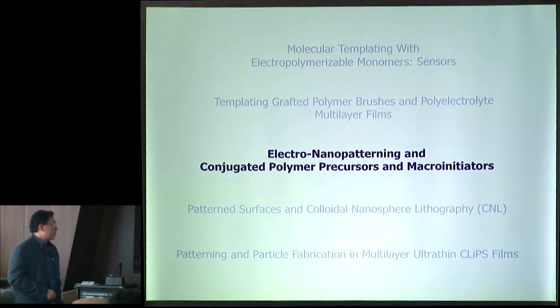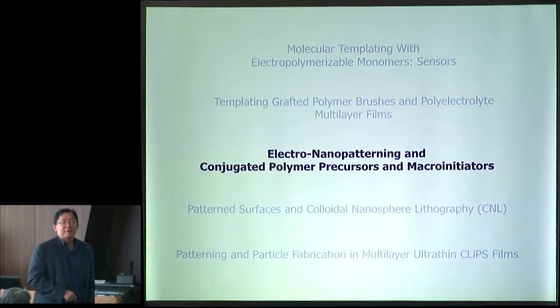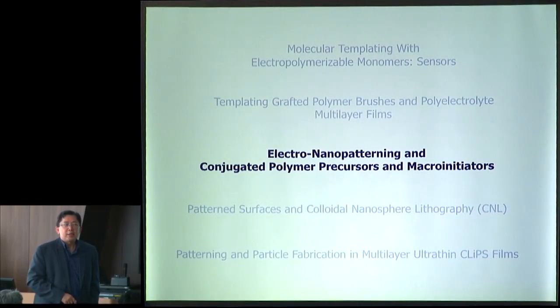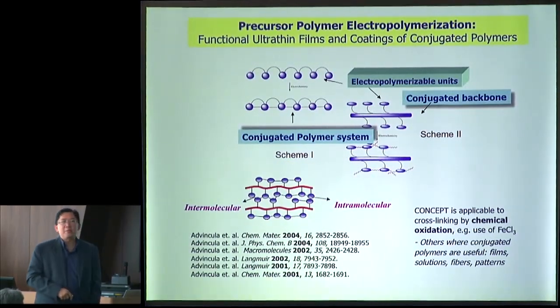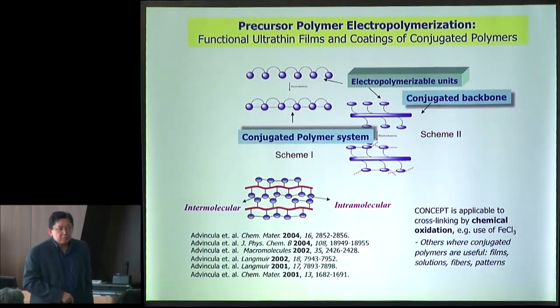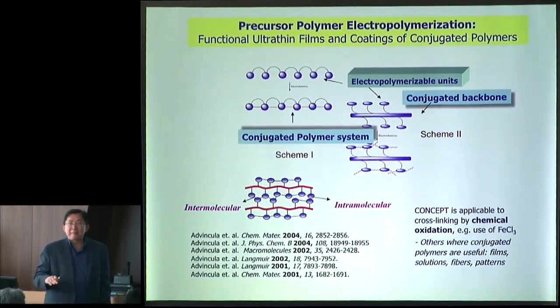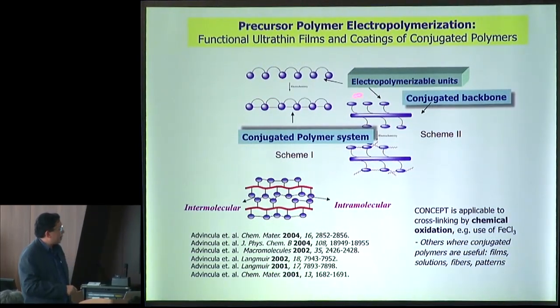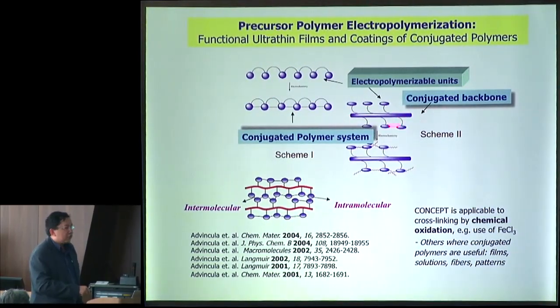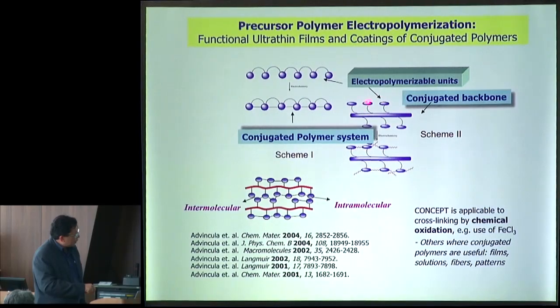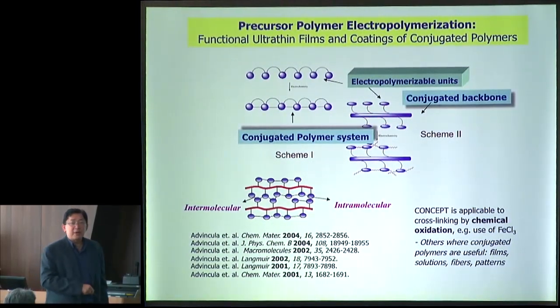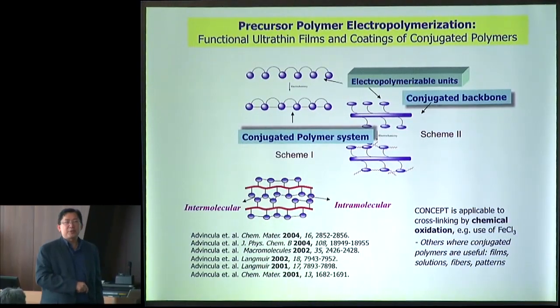Electronanopatterning and conjugated polymer precursors and macroinitiators. One of the things we developed very early in my group is the use of electropolymerized monomers attached to a polymeric backbone. We do this because a polymeric backbone can drive the solubility or even the electronic property. But the presence of these electropolymerizable monomers attached to a polymer means that at one point they can form a ladder polymer, which we don't observe or rarely observe.